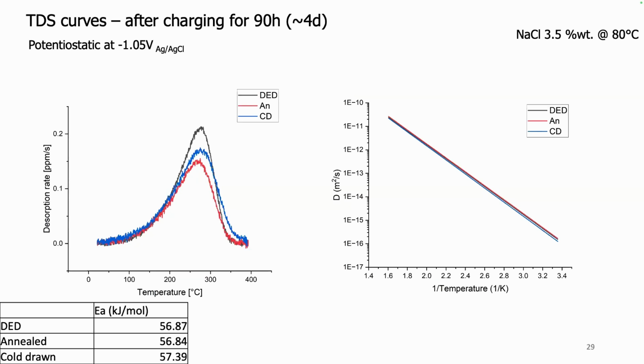All the peaks are very aligned. Again, this is research in progress. We need to get more data. But so far, what we can observe from the activation energies is just purely diffusion. There are no other peaks. We tried extending the temperature range, but there's nothing there. So far, it's not really something about absorption, desorption.